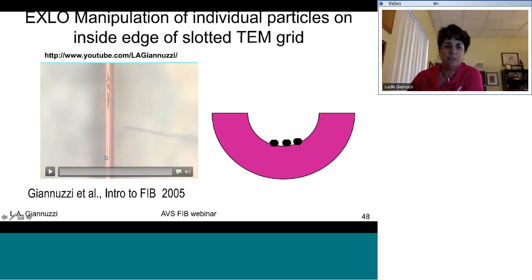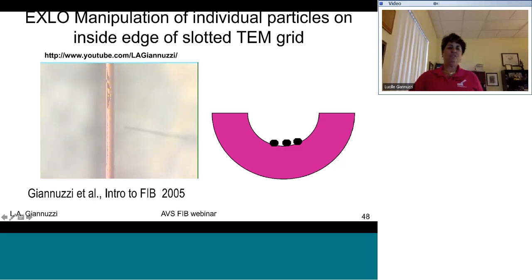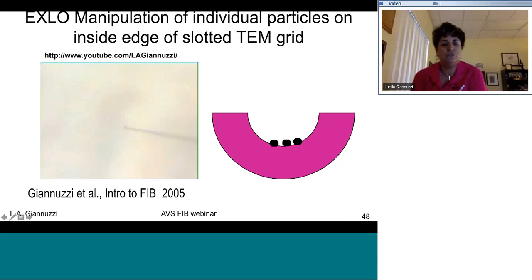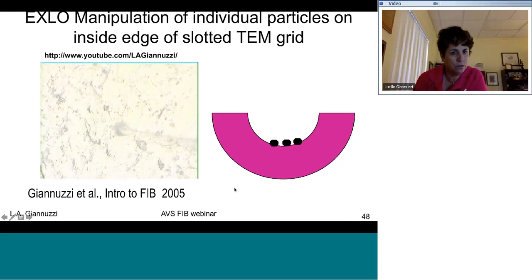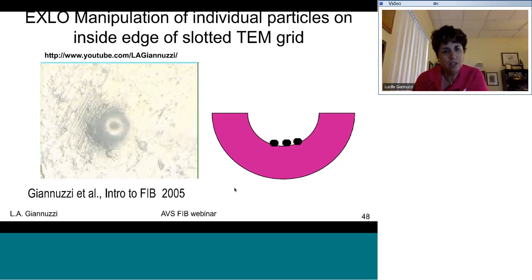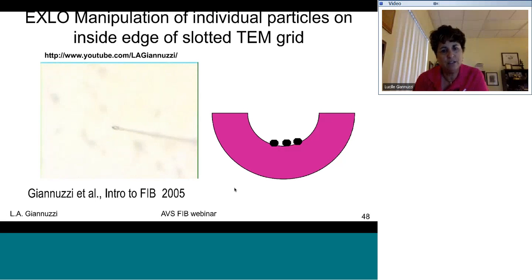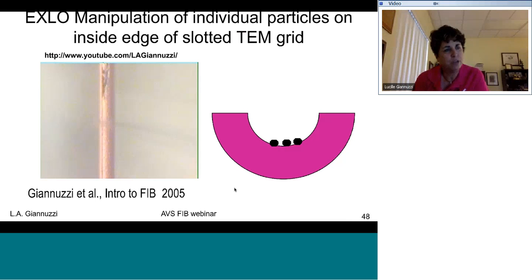And as I mentioned, you can manipulate a lot of things to grids to get them ready for FIB sample prep, to then do the so-called H-bar type sample prep. To facilitate this, you might want to use glue. So this is the probe going into M-bond glue. And now you can use a little blob of glue on the end of the tip as a little paintbrush.